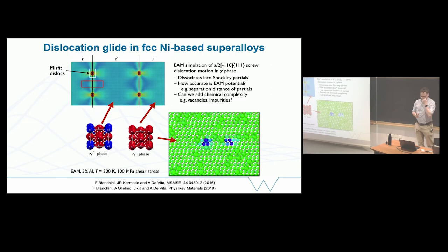We could look at another example. This is a superalloy. So a superalloy is a single crystal turbine blade that you would find in an aircraft. It's maybe about this big, and it's grown very carefully in controlled conditions, so all the atoms are perfectly lined up. It's an FCC matrix. It's a little bit more complicated because it has precipitates inside. So it's basically nickel, but it has hard lumps inside, which are nickel aluminide. These are the gamma prime phases, and dislocations tend to travel freely in the gamma phase, but they can't get into the gamma prime. So we're really interested in understanding the structure of dislocations.